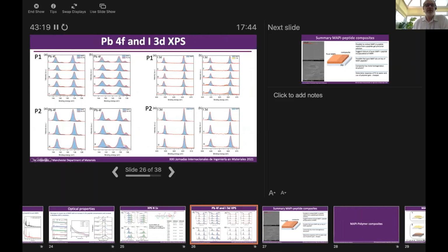We've also looked at the lead 4f and iodine 3d XPS. I'm not going to bore you by going through all of these spectra, but essentially they confirm what we see with the nitrogen 1s, that the high loadings of peptide give us a more stable material, and the perovskite formed in the more hydrophilic peptide has a lower stability.